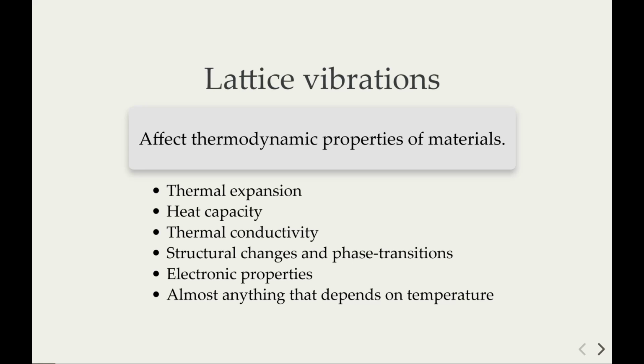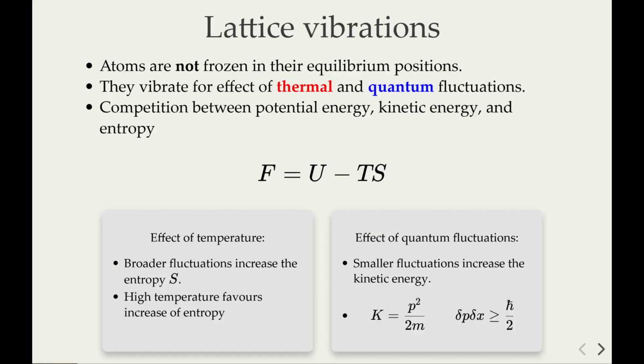Atoms' lattice vibration comes out from a competition in energy between potential energy, kinetic energy, and entropy of the ions. By looking at the potential energy, we want to minimize it, so it's convenient to keep the ions fixed at the minimum of the potential energy. But this is detrimental for entropy and kinetic energy. If you have a finite temperature, the system wants to minimize the free energy.